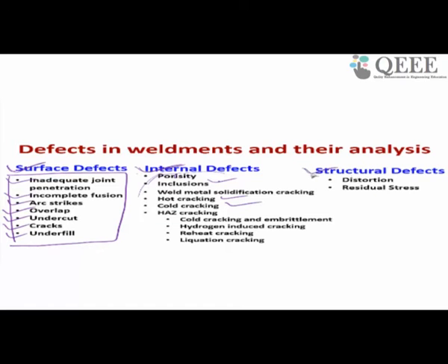Then the third category is structural defects. During welding, what happens? We clamp the material perfectly, then you do welding. During welding the material gets heated up. Because of the heat it will try to expand, but because of the clamping you are not allowing that to happen. As a result, one type of residual stress is developed in the weld material.